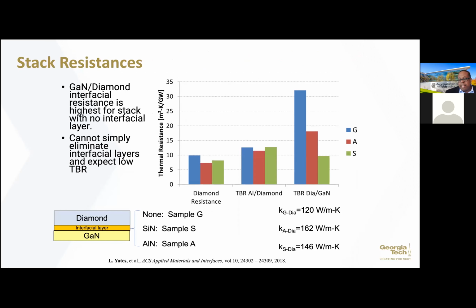So this is a graph that shows you the thermal conductivity, or the thermal resistance, of the diamond layers. There's not a big change between the diamond grown on any one of these interfacial layers. We're measuring this using time domain thermal reflectance. The thermal resistance between the aluminum and the diamond, that's not where you see the change, but what you do see is a large change in terms of thermal boundary resistance between these.